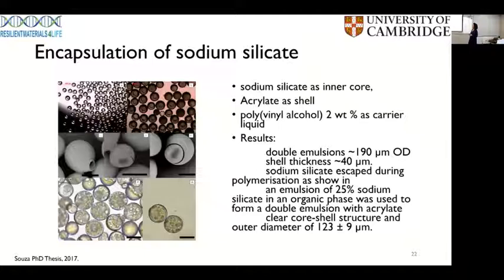And what you can see is that the sodium silicate is so dense. The density of sodium silicate is 1.5 grams per ml. Stick with grams per ml. It's a lot denser than the droplets of the oil. So what happens is that the sodium silicate escaped from the droplets of the oil during the polymerization. That's what you have here, it looks like a mouth opening. It's just that during the polymerization, the sodium silicate was leaking.